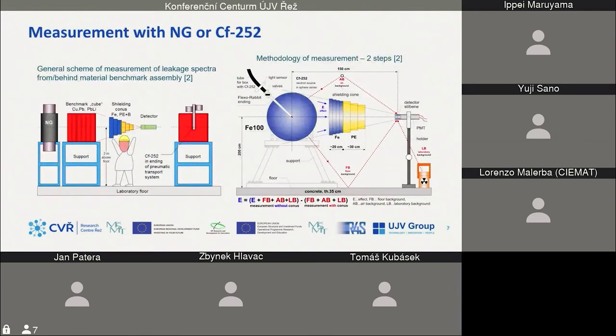It is transported to the middle of some material assembly, which could be a cube, in the ideal case a sphere, or some slab. Then we measure the leakage spectra using the detector. Of course, a neutron generator is much bigger equipment, so we cannot put it inside any assembly. So in the case of neutron generators we also measure leakage spectra, but behind slabs of any materials.